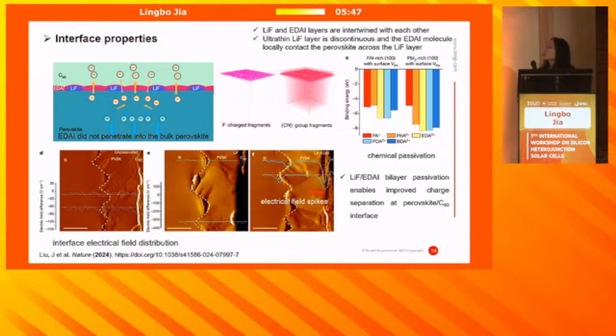Furthermore, we use DFT calculation to investigate the interaction between these materials and the perovskite films. We can notice that the EDAI materials exhibit the higher binding energy, which suggests that it will form a strong coordination interaction with perovskite films by the chemical passivation. And also, we use KPFM measurement to investigate the interface electrical field distribution.